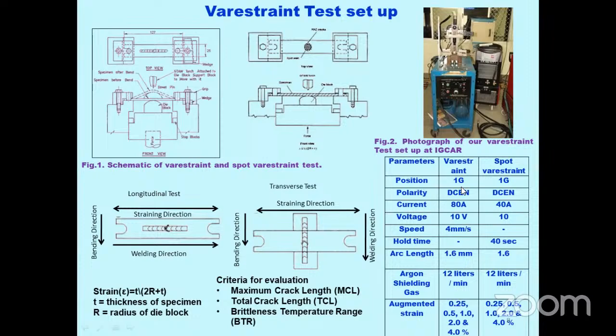The current for this Varestraint experiment is carried out for a partial penetration weld. So for each material, the current and voltage that is applied will change. We don't want a complete penetration weld, but a partial penetration weld. Speed is fixed, and arc length, and shielding gas is argon. We apply augmented strain starting from 0.25% up to 4% strain by varying the die block radius.